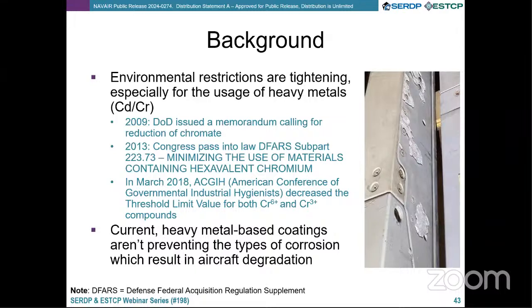It specifically works well on aerospace aluminum and mixtures of metals like aluminum and high strength steel or titanium fasteners. But as you can see on the picture of the right, which was a structural part of a Navy aircraft, even with these heavy metal based coatings, we still see a significant amount of structural corrosion and galvanic corrosion on our aircraft. So the twofold goal is to get rid of chrome, but also improve performance in our protective primers.